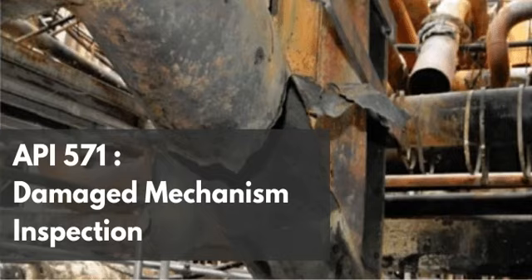It does, and it perfectly highlights that this is an environmentally driven, highly localized phenomenon. It is not a continuous linear corrosion rate. Right, it wasn't just slowly rusting away for 50 years. No, that 4-inch A53 line did not have a manufacturing defect that slowly propagated over 5 decades. It was likely exposed to an environment that hovered just below the critical threshold for the vast majority of its life. We see this all the time with process creep, don't we?